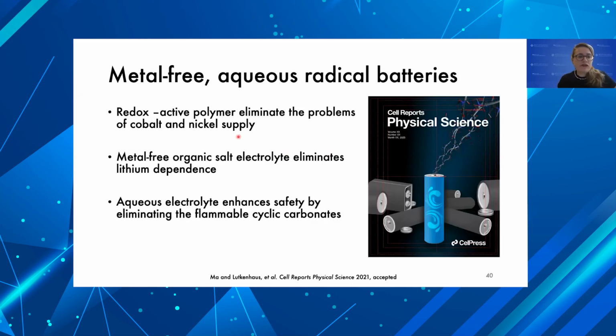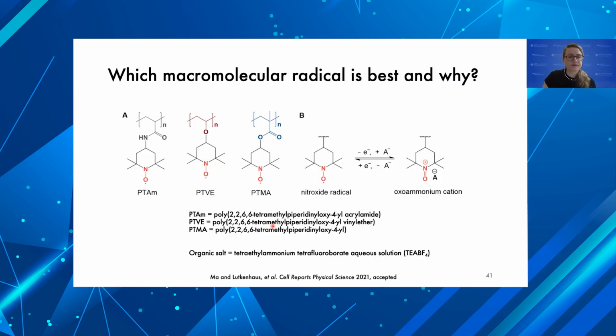Our motivation for this study was that the radical polymer we're working with could potentially eliminate problems in the cobalt and nickel supply. And then by going to an organic salt, we could eliminate or reduce our dependence on lithium. By using an aqueous electrolyte, we can enhance the safety by eliminating the flammable cyclic and linear carbonates that are in today's current lithium-ion batteries. We're not the first to think about this idea of the metal-free aqueous battery, but we're some of the first to explore which radical polymer is the best and why.